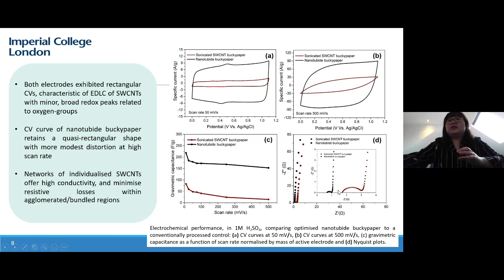Also, the Nyquist plot measured through the EIS technique shows that the nanotube Bucky paper has a much lower internal resistance compared to the sonicated Swin Bucky paper, which also agrees with the conductivity that I showed previously. The improvement in the pore structures of the Swin Bucky paper through the reductive charging actually improves both internal resistance and charge transfer resistance in this case.